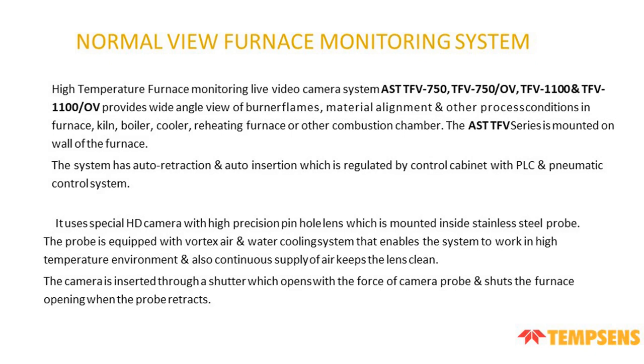It uses a special high definition camera with a high precision pinhole lens tube mounted inside a stainless steel probe. The probe is equipped with a vortex air and water cooling system that enables the system to work in a high temperature environment, and the continuous supply of air keeps the lens clean. The camera is inserted through a shutter which is opened by the force of the camera probe and shuts the furnace opening when the probe retracts.